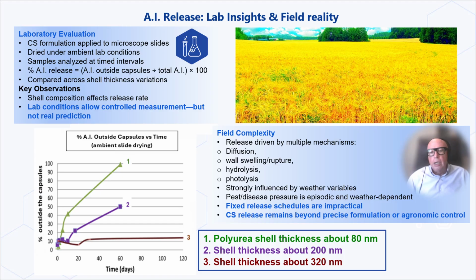AI release, lab insights and field reality. Here's our lab study showing release from three shell thicknesses, 80, 200, and 320 nanometers. Clean curves, predictable behavior, clear differences. We applied CS to microscope slides, dried under ambient conditions, and measured AI release over time. This gives useful insights. Thicker shells clearly slow release rates.